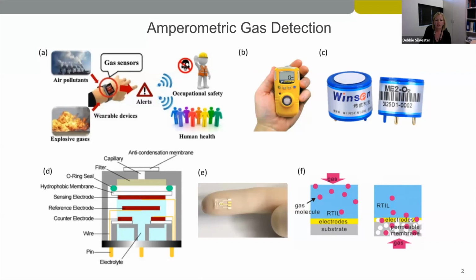So my group and I have been interested over the last few years in using these very cheap, commercially available planar electrode devices, such as shown in figure E. So this is a thin film electrode. This one actually has a gold working electrode and a platinum counter and reference electrodes. And you can see how small the device is on the end of a fingertip. And there's a very thin layer of metal, only about 150 nanometers thick, which means that these sensors are very cheap. They don't use very much of the inert platinum or gold metal, and they're only a few dollars per device.